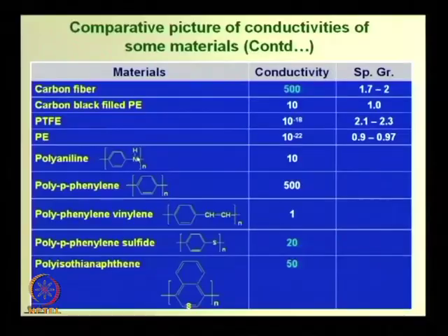Now, you put that polyaniline salt, since it is synthesized in HCl, it will form a salt. Here you see this nitrogen is bonded to hydrogen, here it will form like amine salt, like aniline hydrochloride. Okay. And by virtue of that salt formation, it actually does the protonation. That means, this nitrogen will be protonated. This nitrogen will be protonated. Once this nitrogen is protonated, that has influence on these conjugated electrons, that helps in conductivity.